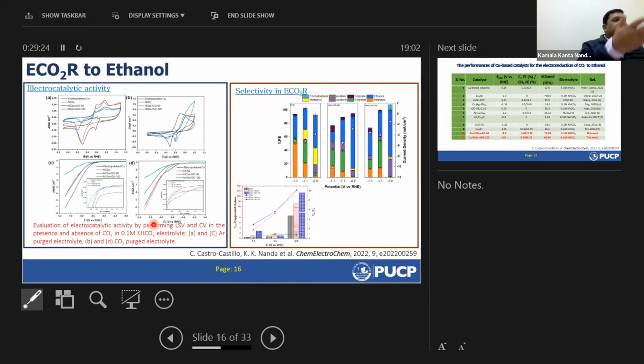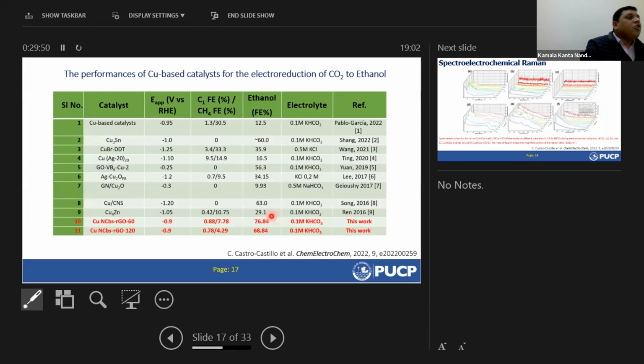When we did the CO2 electrolysis, you can see that this RGO-modified copper oxide copper nanocubes give us a Faraday efficiency for ethanol of 76% at minus 0.9 volt versus RHE. And here you can see the ethanol selectivity over ethylene is drastically enhanced. Okay. We compared our results with the existing catalysts in the literature, and you can see that our catalyst is one of the best catalysts that can produce ethanol from CO2 reduction with high Faraday efficiency.